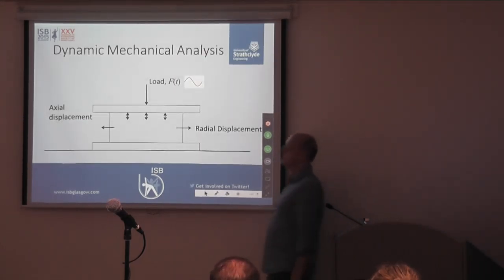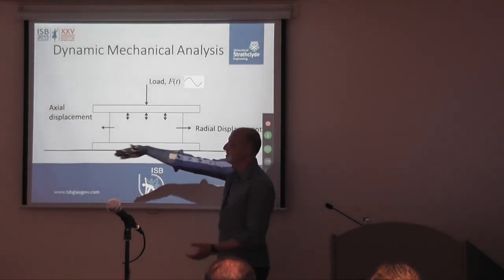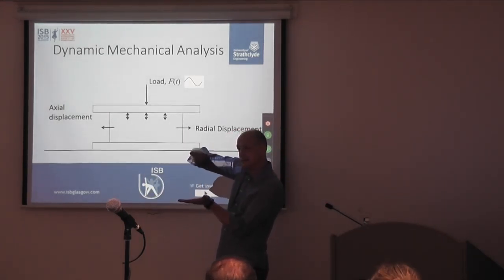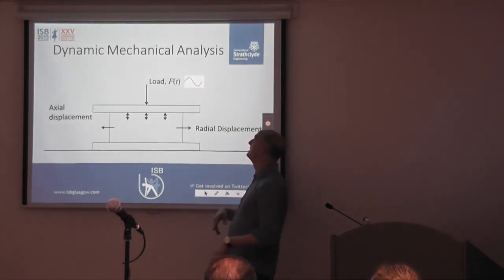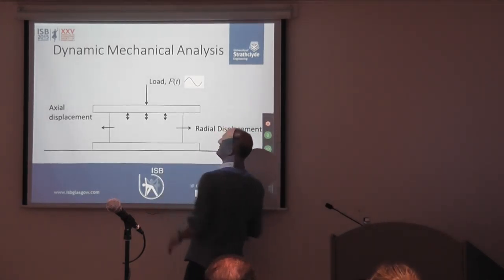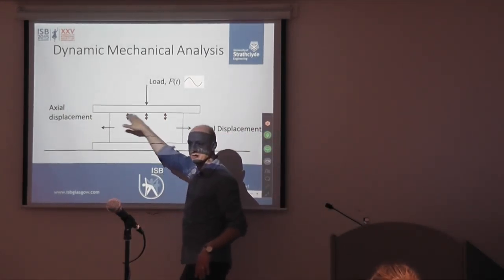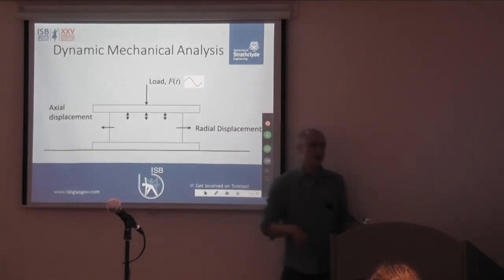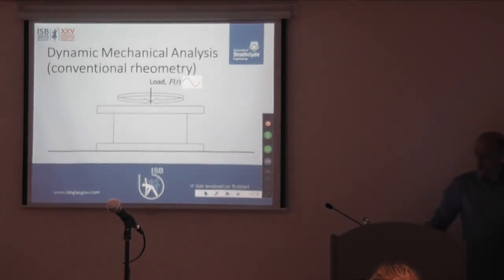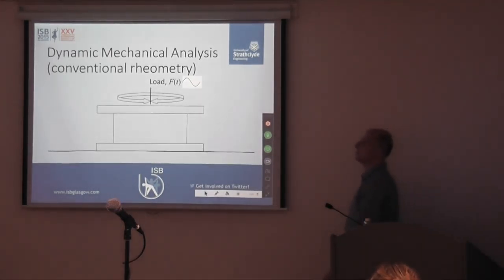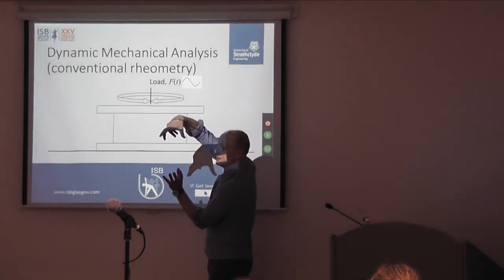Experimentally, what do we do? There's two ways we can do it. Using a machine like this, we can put in a frequency, a nice oscillating frequency, and we can work out that phase difference. Obviously, we get a radial displacement in this way. Slightly dodgy because we're getting frictional issues. Okay, not perfect. The more conventional way of doing it, and this is conventional rheometry, you put a load on it and you put